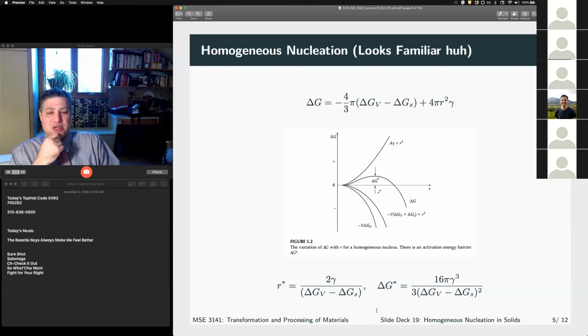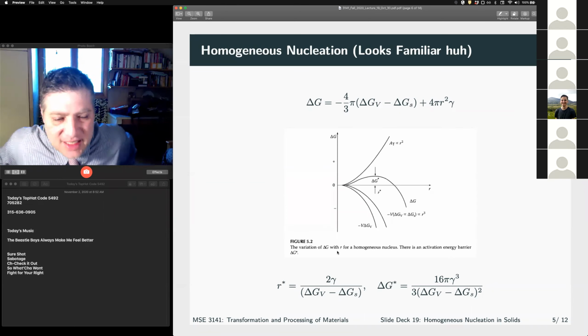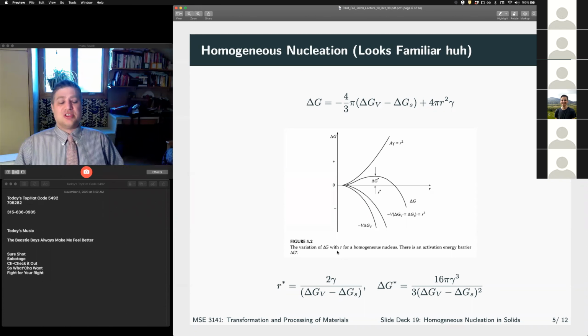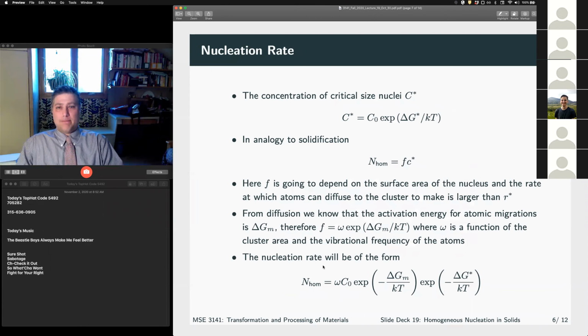Okay, you can see our expression for R star and delta G star are exactly the same as for nucleation of a solid from a liquid, with the exception that instead of delta GV appearing by itself in the denominator, now we have delta GV minus delta GS. Other than that, the theory is exactly the same as solidification, right? Which is why we do that first, right? This is just an added little wrinkle, right? So you know everything there is to know now, right? Well, almost. But you get a sense of the physical picture for nucleation, okay?